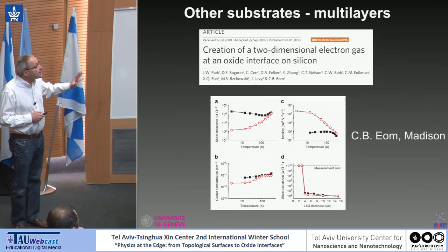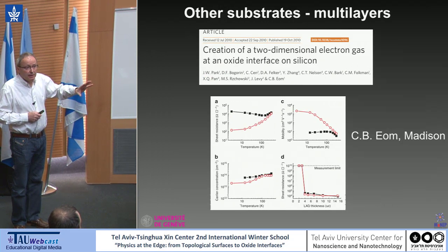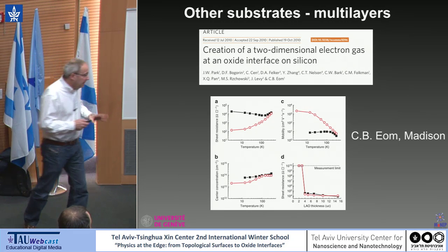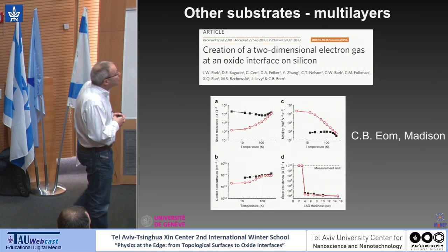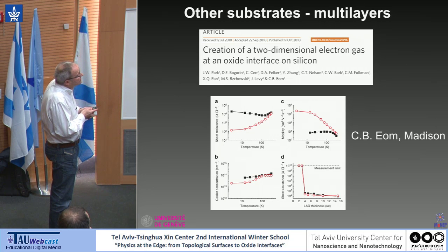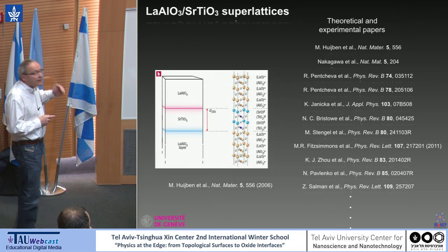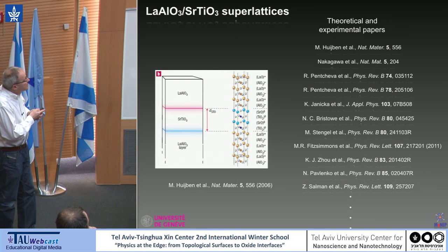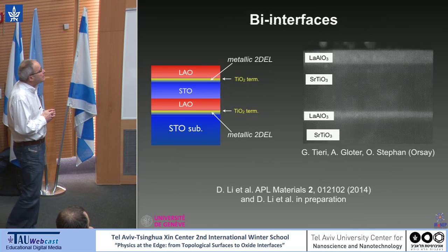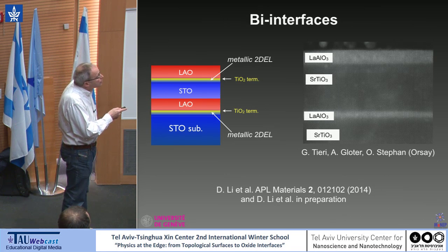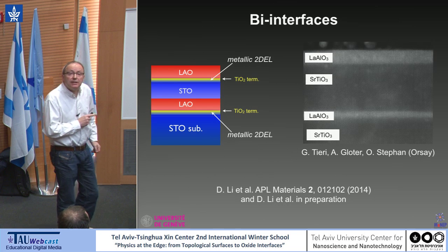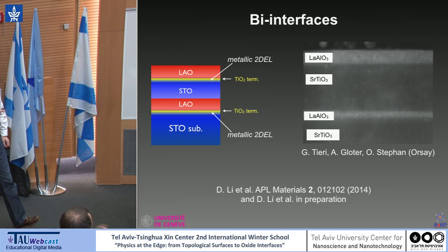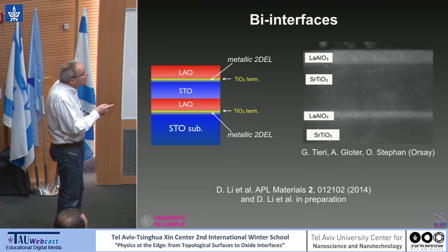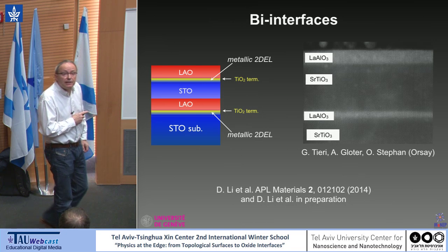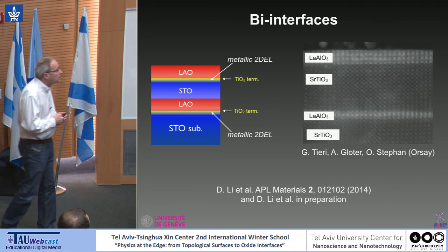Many people try to transfer this interface to other substrates. Not so easy. To this point, it's been very hard to keep the metallicity at low temperature when transferring. This is work from the group of C.B. Eom. People have been trying to make multilayers. It's quite difficult to make sure that every interface is conducting. In Geneva, now we are able to make bilayers with two superconducting systems. And one of the ideas I will not discuss here is to try coupling these superconducting layers and, for instance, see if there is any effect on fluctuations.